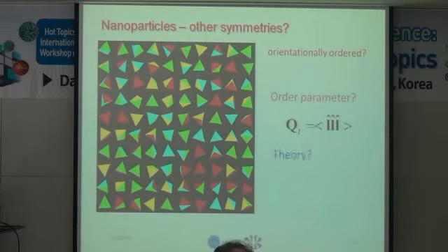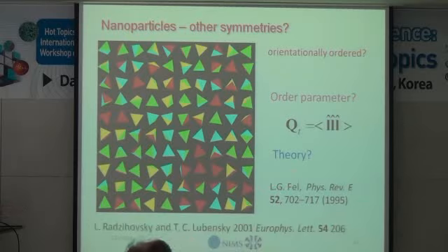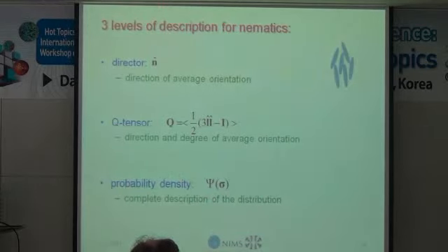But this is already interesting to some extent because we don't know how to decompose third-rank tensors into eigenvalues and eigenvectors and things. And it turns out that there is some theory moving in this direction by Lenny Fel back in '95, and then Tom Lubensky has also done some work on this. So the new kinds of liquid crystals that are emerging have symmetries other than the very simple one that I showed you before, and it's interesting to ask how one would deal with particles of higher symmetry. Okay, so in describing nematics, there are basically 3 levels of description. Some people only talk about the director, other people talk about the Q tensor, and other people still talk about the entire probability distribution function, and one finds these 3 levels in the literature.